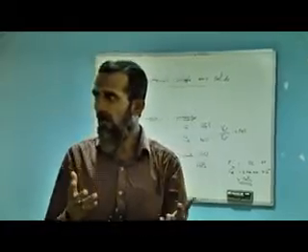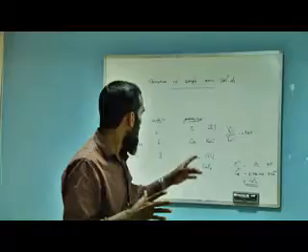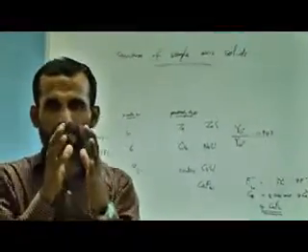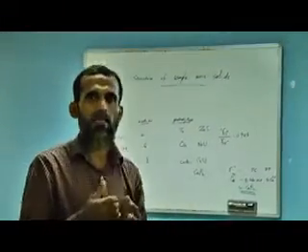So how the sodium ions occupy the void is that the chloride ions will slightly open up and make the void a little bigger than the ideal size, so that sodium ion can enter. So that's the case of almost all ionic solids. It will not be a perfect fit, a perfect close packing.